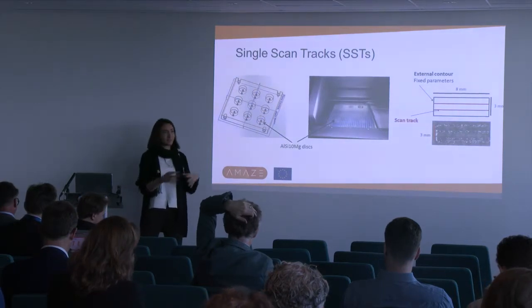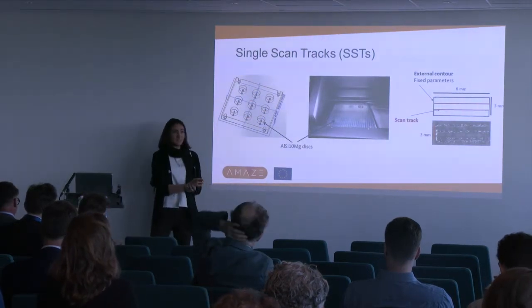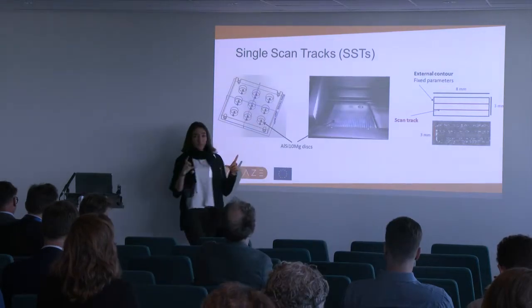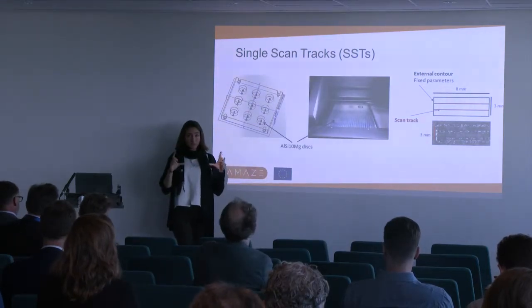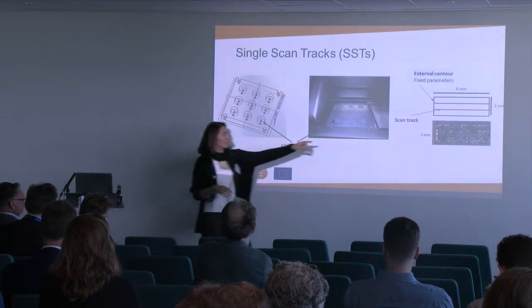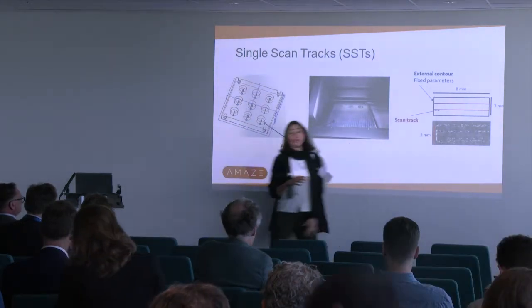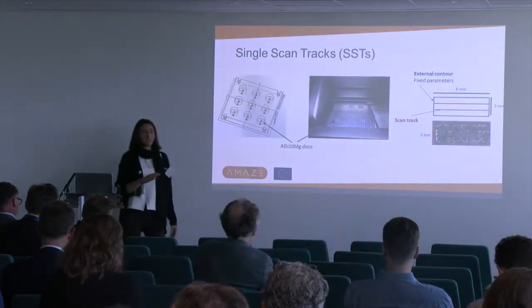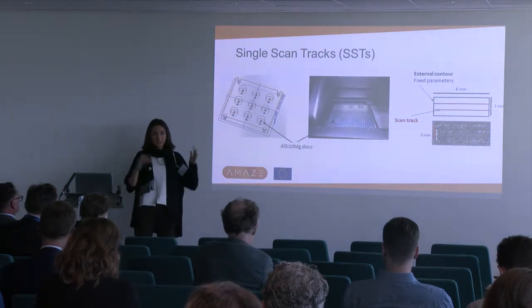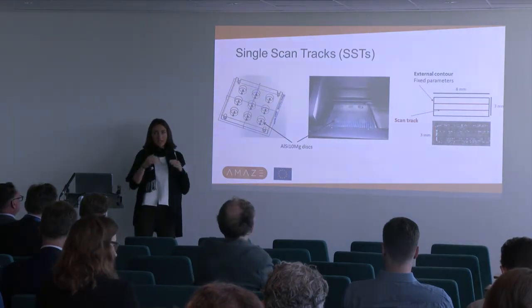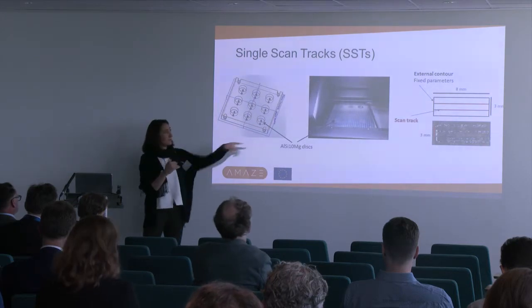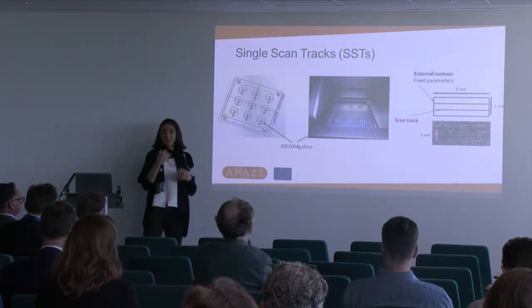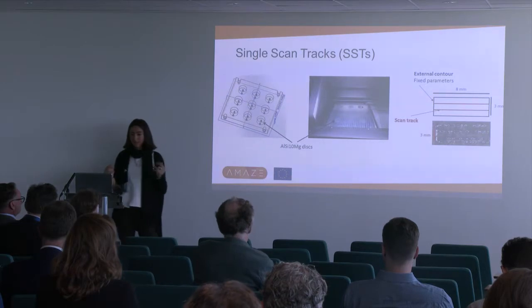The system is quite closed, so it wants to draw a contour of the part, and the contour, which is the black curve here, is done with fixed parameters, so we couldn't change it. So we told the machine to build a larger part with some lines very far from each other. The red lines that we will see inside are the lines that belong to the single scan tracks.